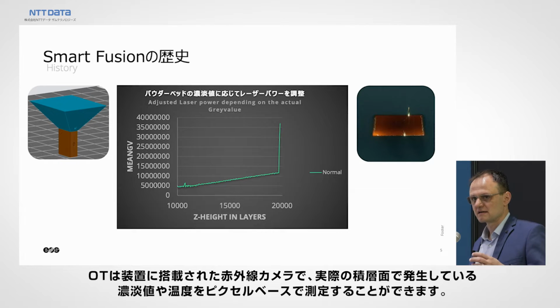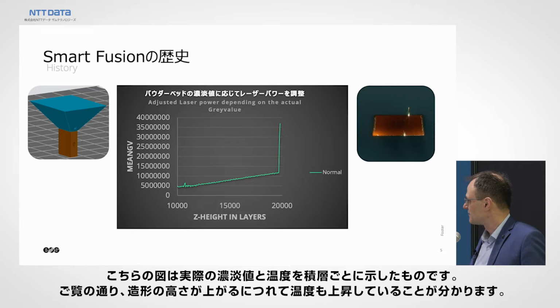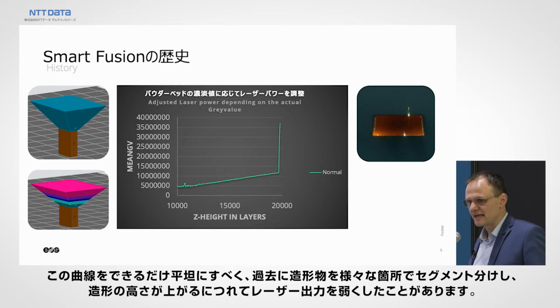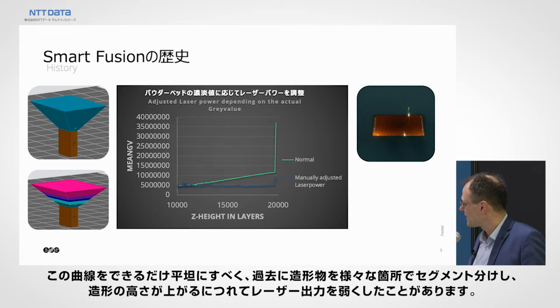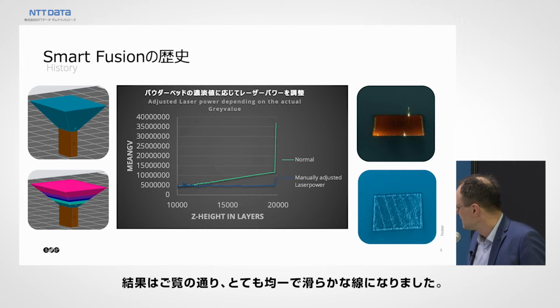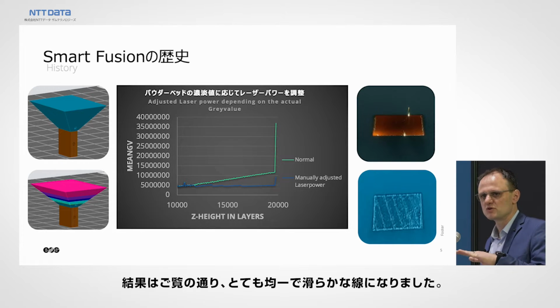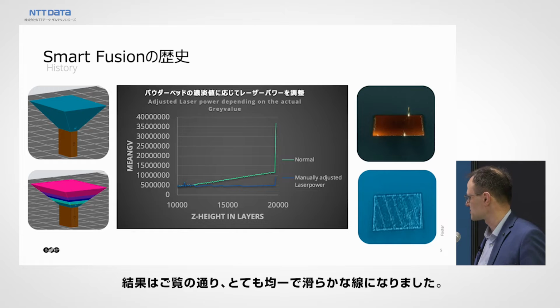Now, OT is an infrared camera installed in the system that can measure the gray value or the temperature actually happening on a layer on a pixel basis. And this is the gray value or the temperature with the rising layers. The higher you build, the more this temperature goes up, and this is something that you typically don't want to see. So our engineers in the past took the part, segmented it into different areas and applied less and less laser power the higher they printed, in order to get a curve that is as flat as possible. And that led to a very homogeneous and smooth surface that you want to see from such a process.